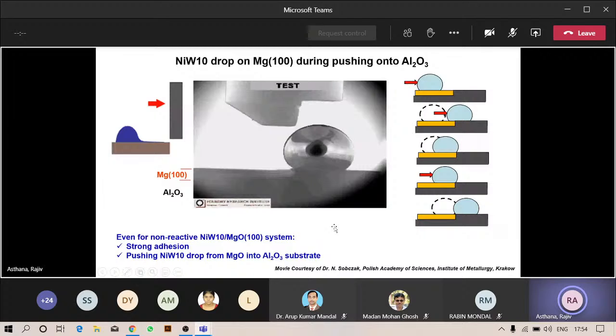Other things that we have tried are rotating the substrate while squeezing the liquid, so you can actually shear the liquid in contact with the substrate and examine the behavior, or you can transfer the droplet from one substrate to another. These things are easy to do for low temperature systems, water or organic, but very hard to do for high temperature systems.